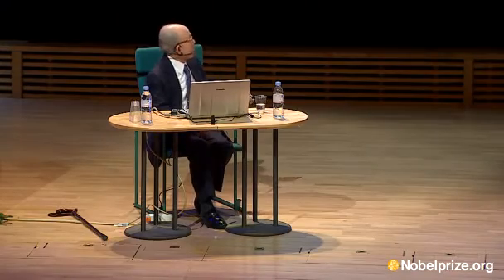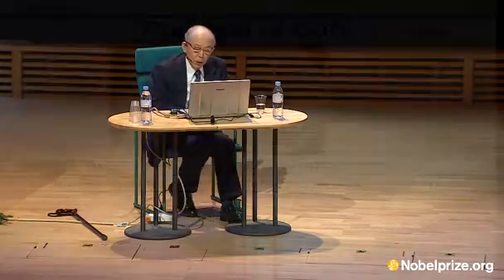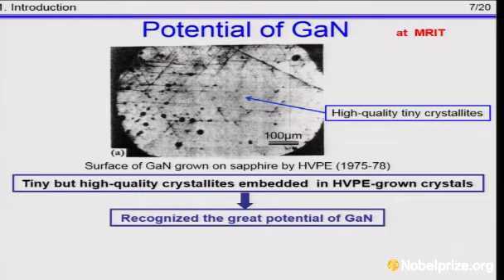During this work, I recognized the great potential of gallium nitride as a blue luminescent material. When I found tiny but high-quality crystallites embedded in a gallium nitride crystal containing many cracks and pits, I was intuitively convinced that conductivity control, even p-type crystal, should be achievable if this kind of quality over an entire wafer could be made.